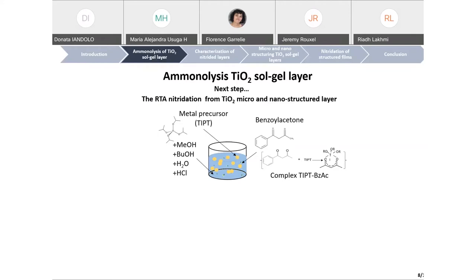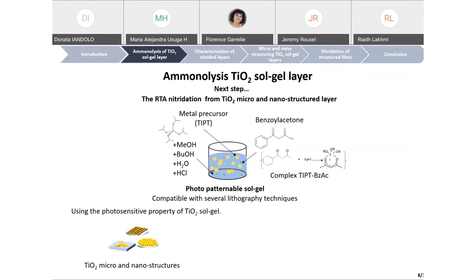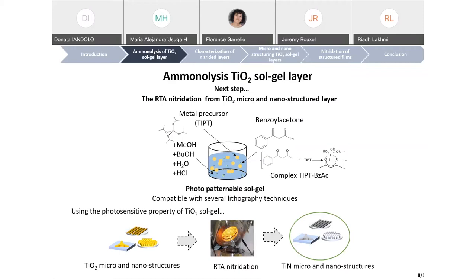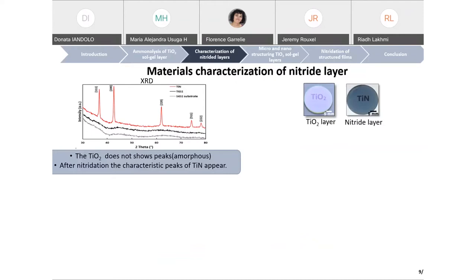This photopatternable sol-gel is compatible with several lithography techniques. Using the photosensitive property of the sol-gel and the different lithography techniques, we want to obtain titanium dioxide micro-nanostructures. Using the RTA nitridation, we want to transform the titanium dioxide micro-nanostructures into titanium nitride micro-nanostructures, using a simple lithography and nitridation method without the deposition of a sacrificial layer or an etching process. At first, we do the characterization of the nitride layer without any microstructuration.